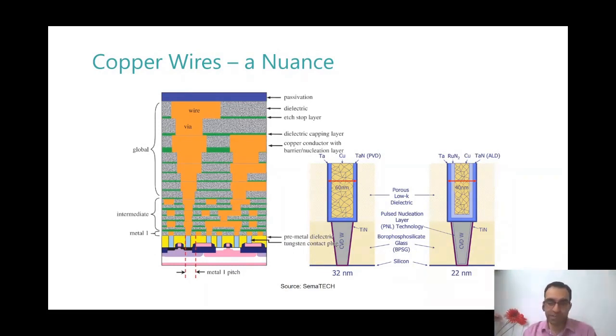Because we understood that copper can diffuse into silicon and can lead to those intermediate states and completely spoil the functioning of your device. For copper, you need to be extremely careful and you need to put a barrier around copper wires so that copper doesn't diffuse out of the wire region. Otherwise, copper will very easily diffuse into the oxide and from oxide it will very easily go into the substrate also.